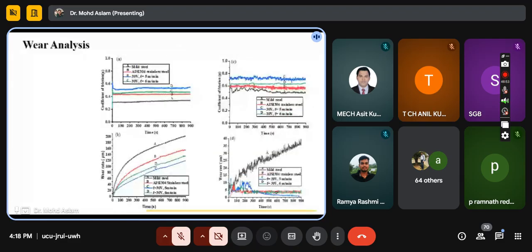So here I have conducted some wear analysis with the help of our cladding manufacturing technique. We have observed that in the case of mild steel, the wear rate is higher as compared to steel, and silicon carbide and steel MMC. So easily we can understand that steel improved the wear resistance, corrosion resistance, along with the hardness also. But if we are using silicon carbide with steel, it developed more wear resistance as compared to steel.